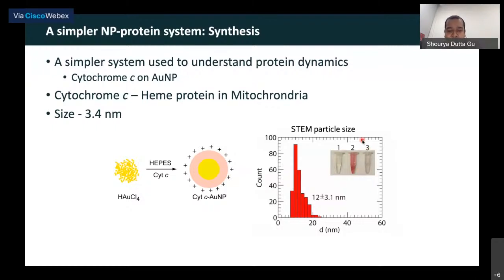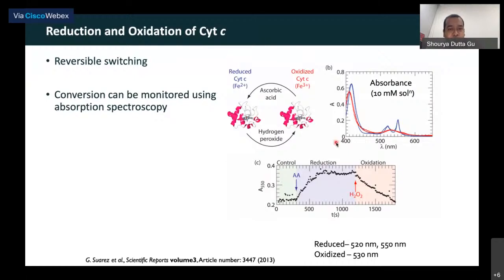So now the idea is, can we analyze these particles to show that we have the cytochrome C molecules on these particles, right? So typically, if you want to detect cytochrome C, if you look at it in literature, what people do is they use UV visible absorption spectroscopy, right? So in that, this is the typical UV-vis absorption graph of cytochrome C. So the horizontal axis is the wavelength and the vertical axis is the absorbance, right? So now cytochrome C is a heme molecule. So iron can be in two states. It can be in either Fe2+ or in Fe3+, right? So now if cytochrome C is in the reduced state, you will have two peaks around 550 nanometers shown in blue. However, if cytochrome C is in the oxidized state, you will have a single peak around 530 nanometers as shown in red, right?